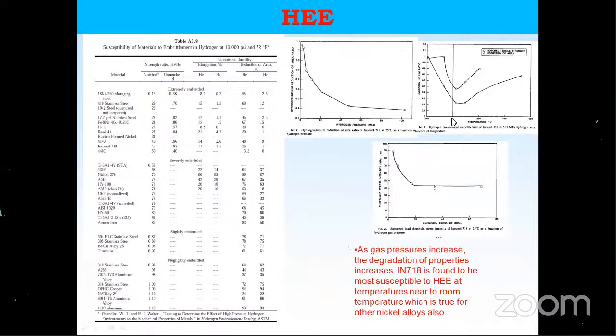At room temperature, from minus 50 to plus 150 degrees, the maximum degradation is happening. If you go to very low hydrogen temperature, no issue. Very high temperature also, there is no issue. It doesn't happen. But the effect is happening when the material is exposed to hydrogen at near room temperature.